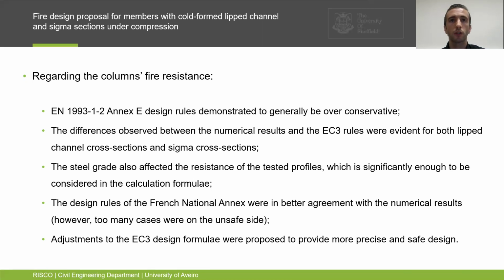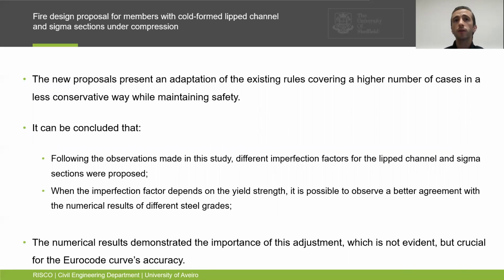However, too many cases were on the unsafe side. Adjustments to the Eurocode 3 design formulae were proposed as an adaptation of the existing rules, covering a high number of cases in a less conservative way while maintaining safety. Different imperfection factors for the lipped channel and sigma sections were proposed. When the imperfection factor depends on the yield strength, it is possible to observe a better agreement with the numerical results of different steel grades. And the numerical results demonstrated the importance of this adjustment, crucial for the Eurocode curve's accuracy.